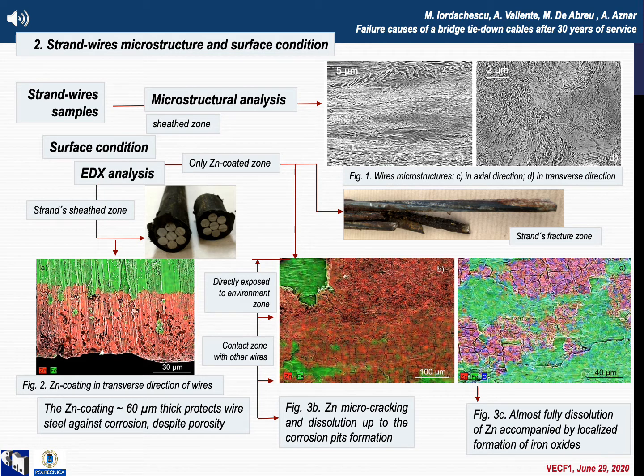Figure 3c shows a higher damage level in the zinc coating up to its full dissolution in the strand wire outer surface, together with the iron oxides formation in the unprotected regions of the wire steel.